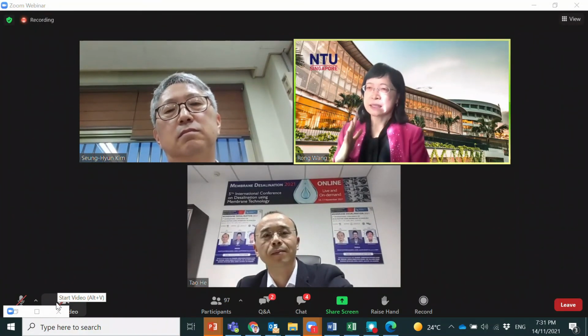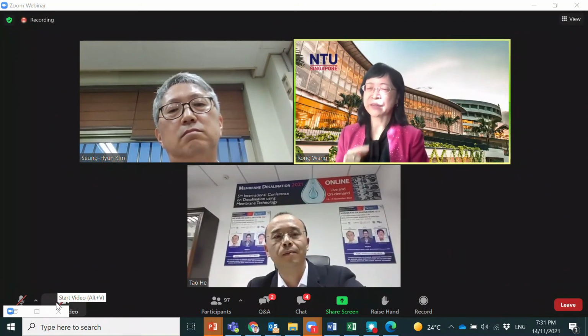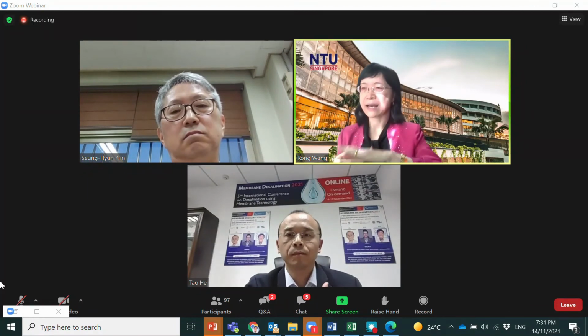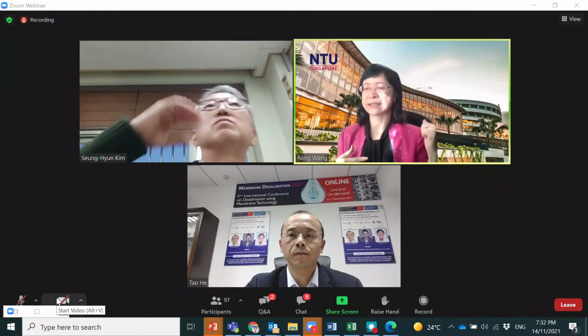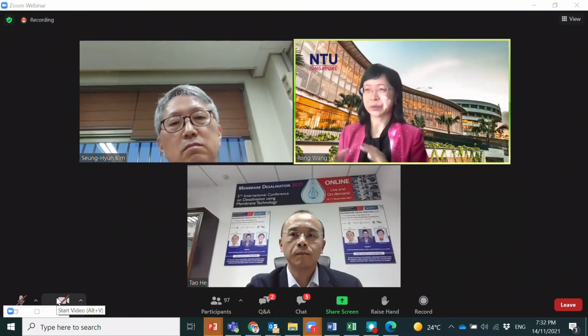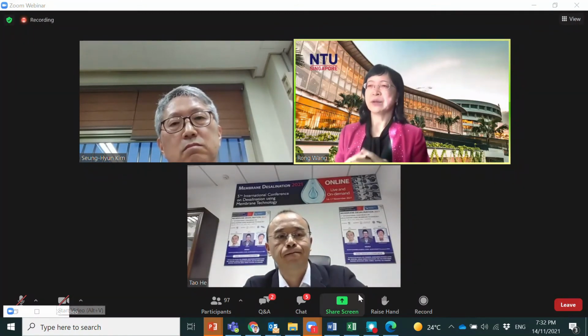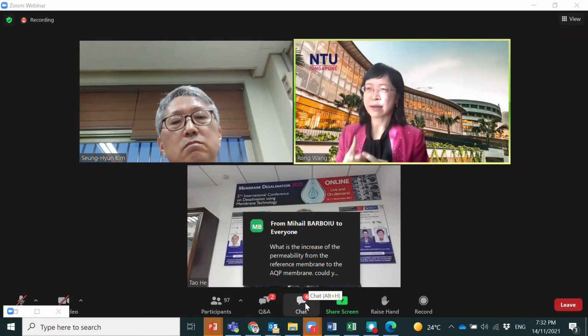Okay. Currently in the lab, we have done long-term testing for 70 days, non-stop. The membranes were tested in parallel with the commercial membrane in the same system. This means they have 4 cells in parallel, testing non-stop using real seawater that we collect from the PUB seawater desalination sites. And after 70 days, no issue, very stable. And actually, after we scale up, we have one task to run the pilot system for half a year. That's the task given by the PUB, the funding agency. In that way, we can demonstrate the long-term stability.